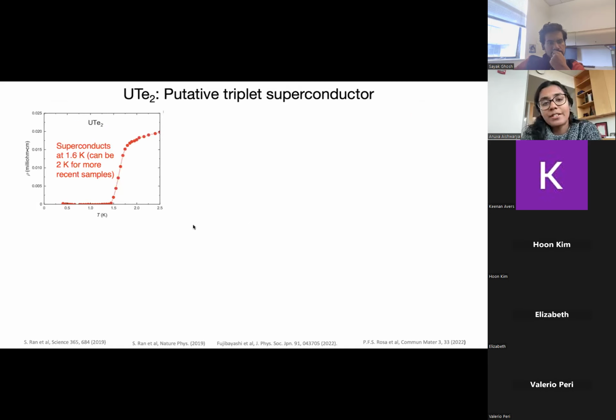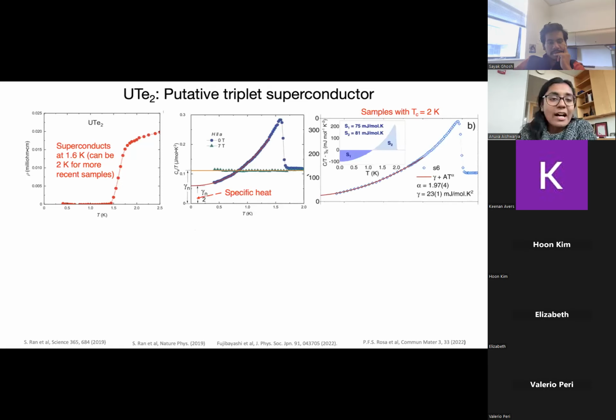However, the more interesting properties of UTe2 are in its superconducting state. Some initial samples in 2018 had a TC of 1.6 Kelvin, but when people perfected their recipe, it could be pushed to 2 Kelvin for some more recent samples. Specific heat shows a large jump and a large residual Sommerfeld coefficient, which indicates quasi-particles in the superconducting state. This Sommerfeld coefficient is also tied to the TC and the sample quality, as we expect. So it goes down in some more recent samples, but doesn't go all the way to zero.